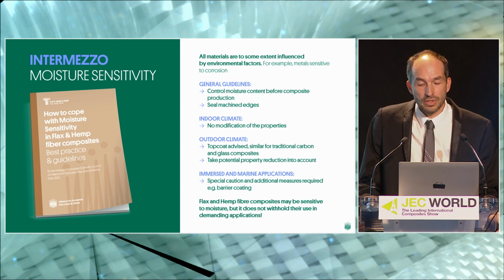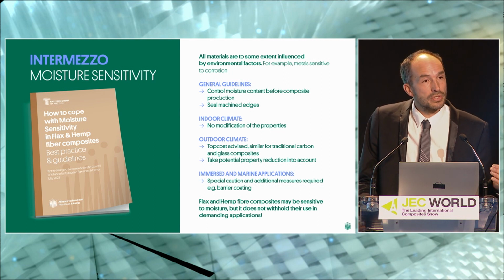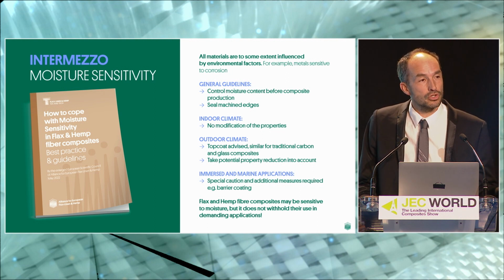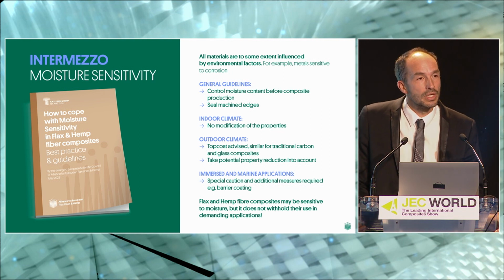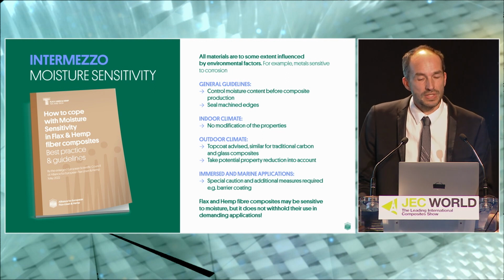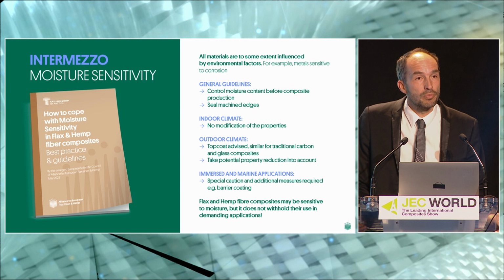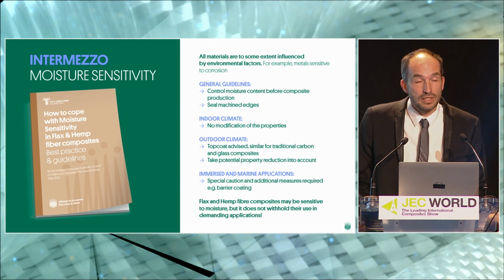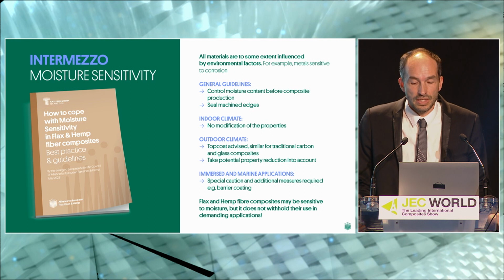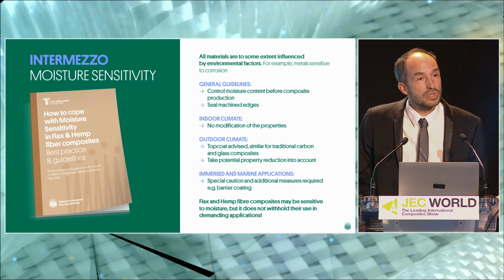And depending on the use conditions, for example, for indoor climate, we have not observed really modification of the properties of the composite. We can see that even if the moisture content increases, when the composite comes back to the equilibrium, we have a reversibility in the mechanical properties. For outdoor climate, we have more severe conditions, and then it's advised to use a top coat, as it's done for carbon and glass composites, for example, but also to take into account the reduction in elastic properties and strength in the design and in the sizing of the parts.